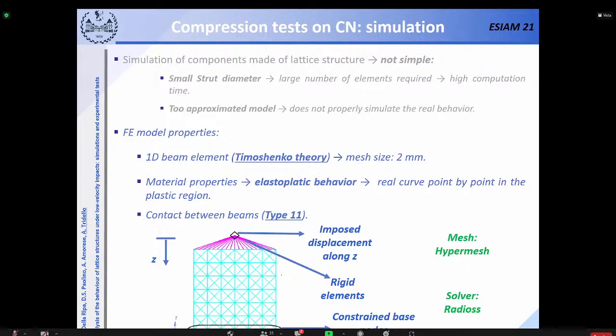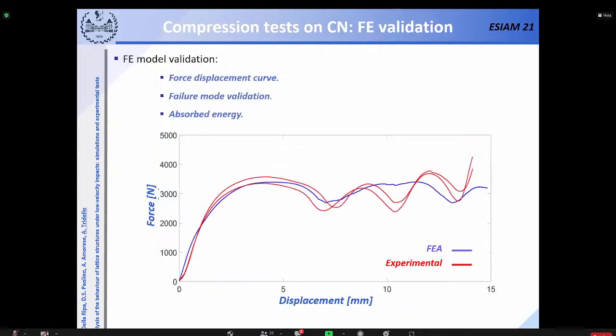Yeah, we indeed ran quasi-static tensile tests on specimens in carbon nylon, and we got the stress strain curves, and then we implemented the real curve, the actual curve in the model, so that it's a specific model for that carbon nylon specimen and material. This is, in our opinion, was the best way to catch the complete behavior. And indeed, we didn't model the anisotropic behavior of the carbon nylon, but indeed we got good results in terms of modeling.